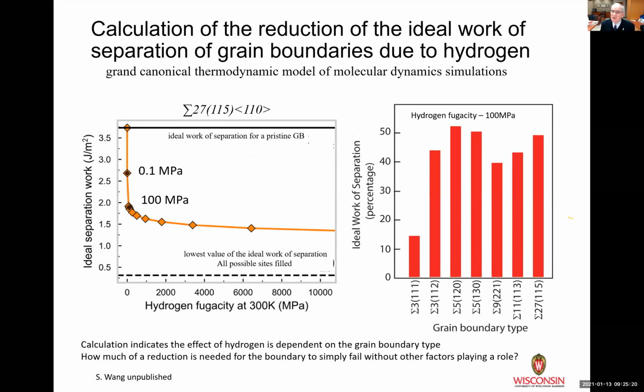So I said at the beginning, one of the things I think that you're incredibly unfortunate in being this time is that you have all sorts of different tools at hand that you can apply to the problem. So this is another work from Shuai, and he has been using this grand canonical thermodynamic model to look at what's the reduction in the cohesive strength of a grain boundary due to the presence of hydrogen. And you can see his results here on the left. You pump hydrogen onto the grain boundary, you do decrease the cohesive strength. If you put enough on there, you'll decrease it a lot, and yes, it will fail.